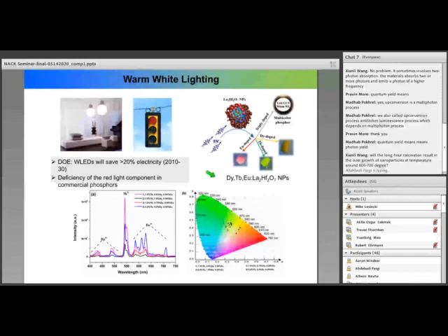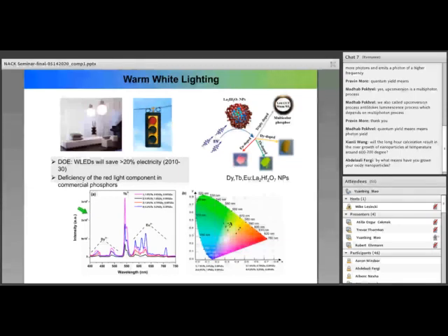And then you see, when we adjust the ratio, the doping level of these three elements, the emission corresponding to these three dopants actually changes. So one thing is, the emission from these two dopants can also excite the Europium 3+ process well, other than the excitation source we use, right? So that's why, with that composition, we get warm white light emission, as we're showing in this diagram.